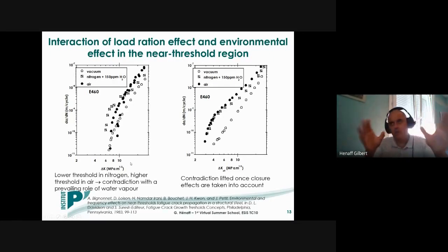So this can look contradictory with the fact that we assume that water vapor is responsible for the highest fatigue crack growth rates in most environments. But actually, this results from more complex interactions between the fatigue crack growth process and environmental effects, especially, as we will see, due to the formation of an oxide layer on the crack flanks that will promote crack closure effects. And indeed, as soon as we are able to measure and take into account the crack closure effects by estimating the delta K effective value, you can see that we have something which is, again, consistent with the prevailing role of water vapor, since the lowest crack growth rates are obtained in vacuum.